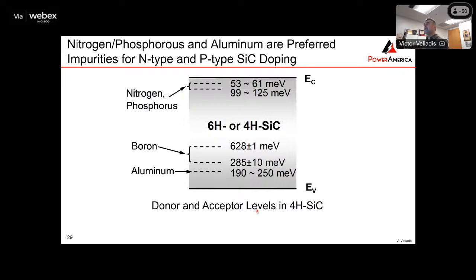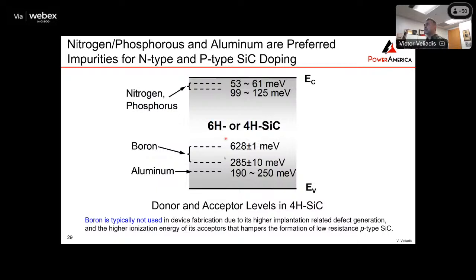And we need to have shallow dopant species. So for the P+, aluminum is best because it's relatively shallow compared to boron. And in the case of the N+ doping, you have a shallow level for nitrogen as well as phosphorus. They're relatively close. Boron is not typically used because it's not very shallow, and also it has a lot of defects, and that stops you from getting a low resistivity contact. So it's almost exclusively aluminum for the P+ in silicon carbide.